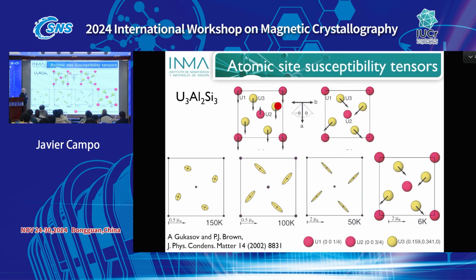They were not able to distinguish the magnetic structure on one side and the other, but they measured the magnetic susceptibility tensors as a function of temperature. When the system decreases in temperature before arriving at the ordering, they determined a strong anisotropy of these tensors along these directions. This is a proof that the final magnetic ordering is like this one.